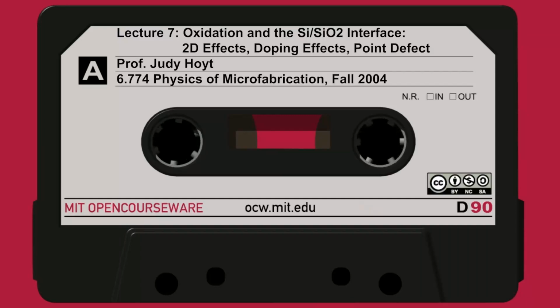So it seems maybe to your eye initially, oh, what's the big deal of that? But when you go to simulate how these devices electrically behave, it makes a big difference. So the stress effect here comes in because, again, you have this curved surface that needs to stretch. And there's stress buildup whenever you have a corner. And that tends to lower the oxidation rate. And that's also been observed experimentally.